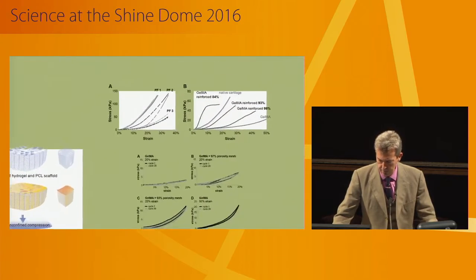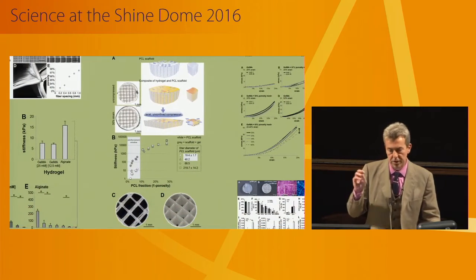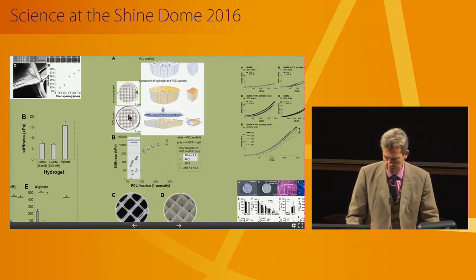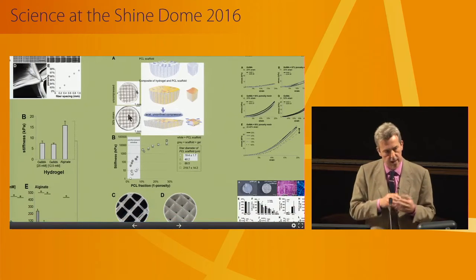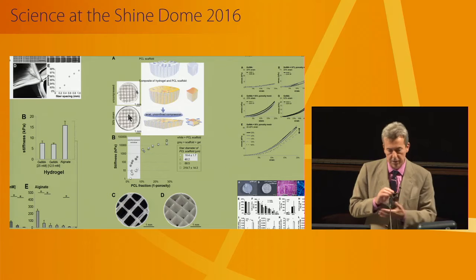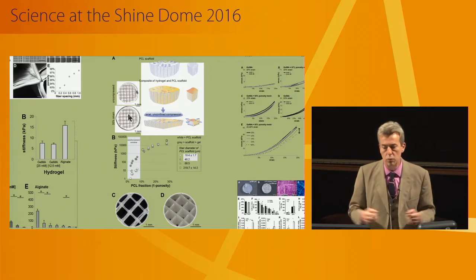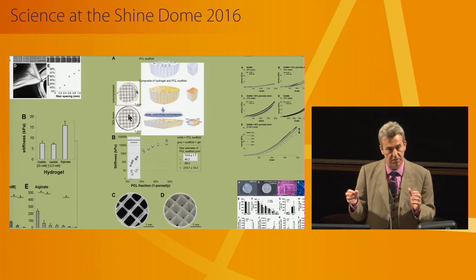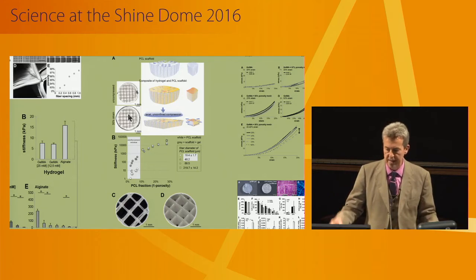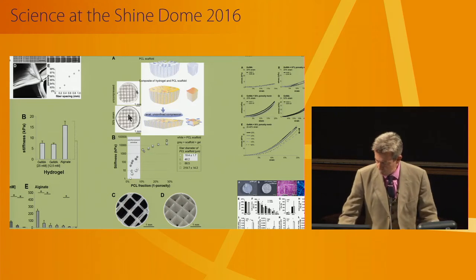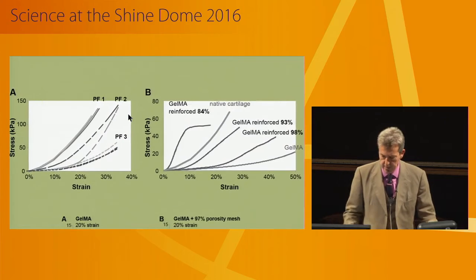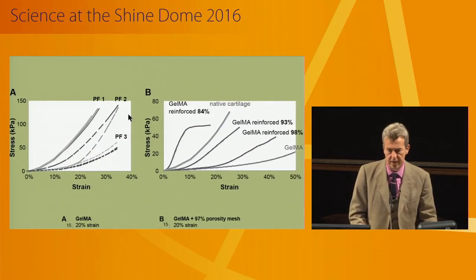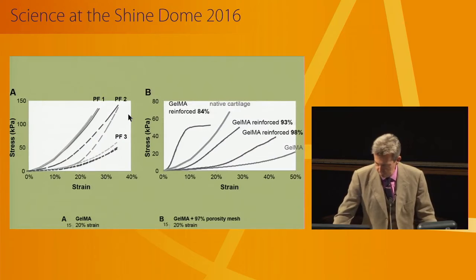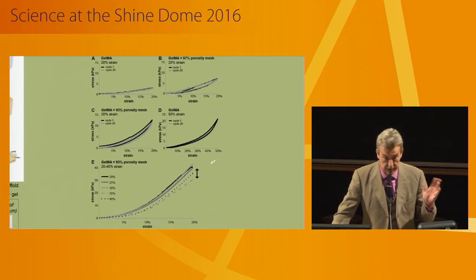So how does that work? The way it works is that on the specific designs we do, these box structures, when you place the hydrogel inside, the hydrogel maintains a lot of water, and if you put this under compression, the water tries to move out, but the water can only get to the fibers, which are put under tension, and that's how you increase these mechanical properties. And again, we have tested this in quite detail. Here you see the graphs for different strain rates. We do this with different bioinks, different biomaterials, and depending on the biomaterial, you see this increase of the mechanical properties between 20 to 50 times.